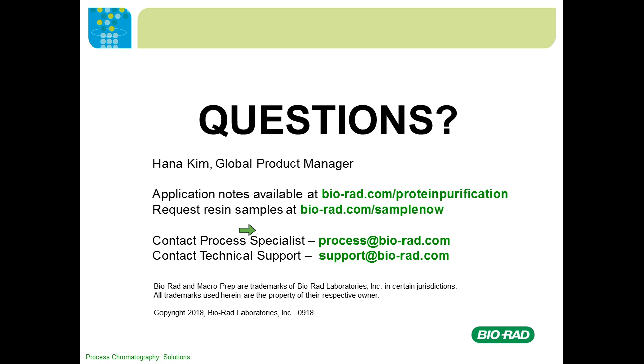The main difference between Nuvia Q and HPQ is that Nuvia Q was developed for high binding capacity for most biomolecules, for example, where the molecular weight is not as big as the large molecules. Therefore, the main difference between these two resins is that one has an open pore structure, and in the other the pore is filled with the gel phase functional group. The gel phase is able to increase the binding capacity of the biomolecule, but we also found this gel phase starts to eliminate the mass transfer for large biomolecules. That's why we improved our technology to develop an open pore Nuvia HPQ specific for large biomolecules.